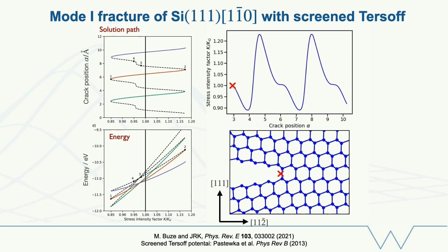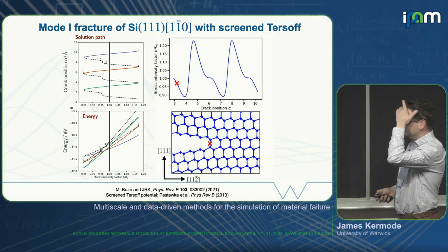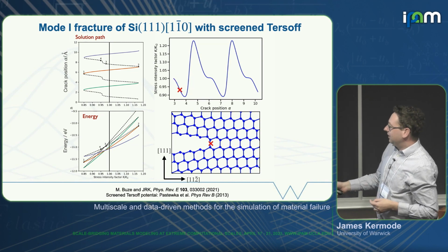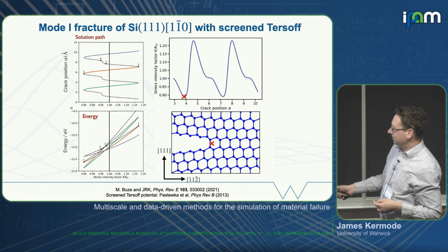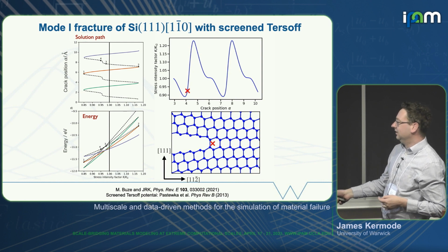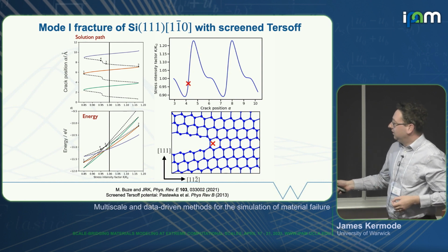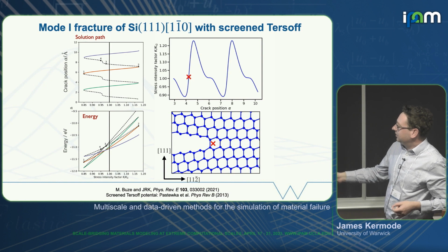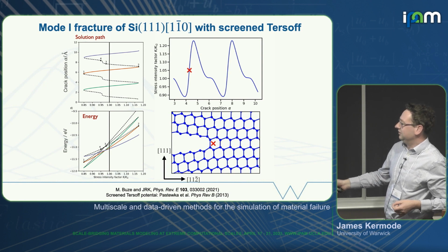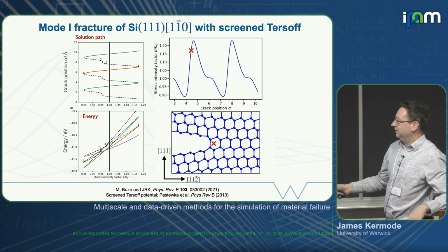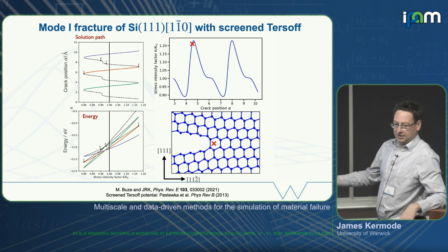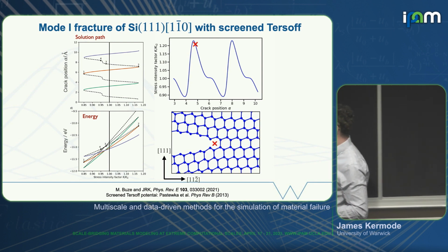This is silicon again, 1-1-1 cleavage plane. And these are the solution paths that we get. I think I'll start the movie while I'm talking through it because it takes a little while to play. So here we're following a solution path. This is the crack position. You can see the crack position updating in the movie at the bottom as well. Now we're on the stable part of the bifurcation diagram of the solution path. So the crack position is increasing as the stress intensity factor increases. That corresponds to the successive green, orange, and purple portions of the graph here.